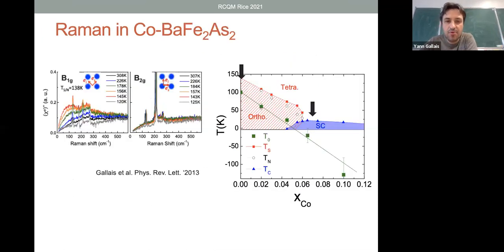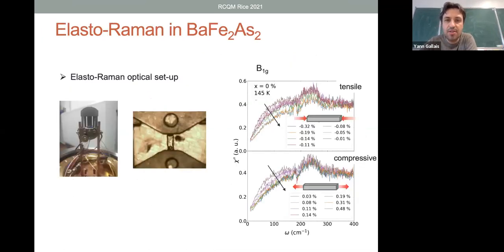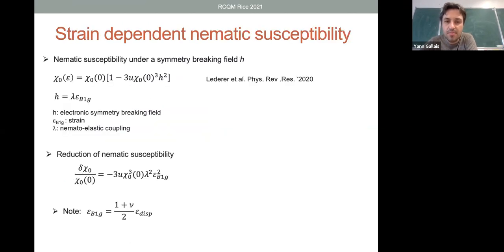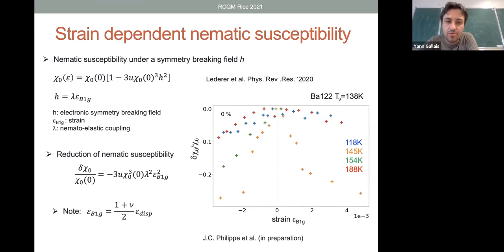So let me just briefly show you this. This is an example of barium 122 under uniaxial strain close to TS. And you see that both under tensile and compressive strain, there is a decrease of the low energy quasi-elastic peak. And this decrease can be converted into a change of nematic susceptibility. So this is the plot here I am showing you.